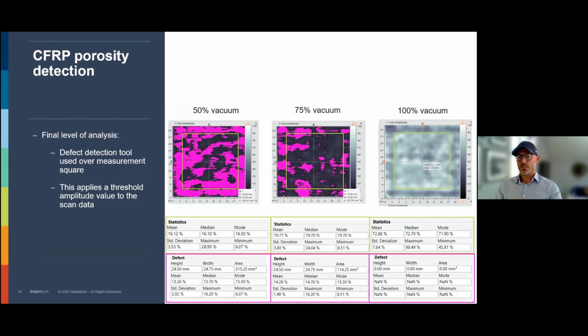So you can set it up with some requirements. You can, for example, set on the back wall, calibrate it with a perfectly healthy, good 100% vacuum sample and say, we will approve everything that is between 40% and 80 or 100% back wall reflection, right? And then everything under that we set as pink, so it will be very easy to detect. And that's what we've done here. So you can see the 75% vacuum has a lot more pink, and you know that that's bad and not approved. And 50% vacuum, you have a lot more pink, which is even worse.